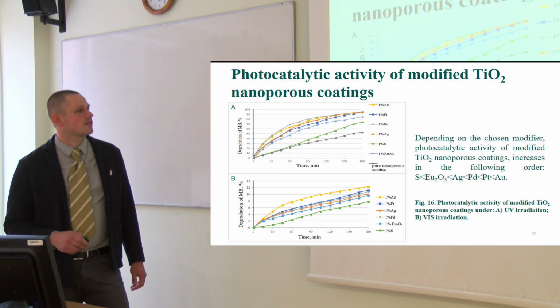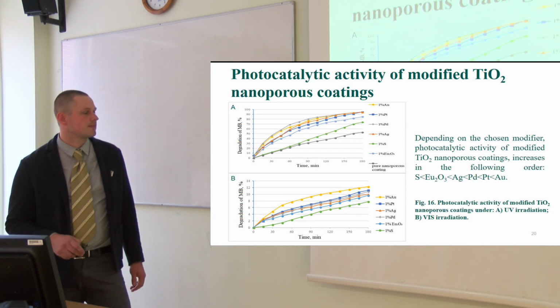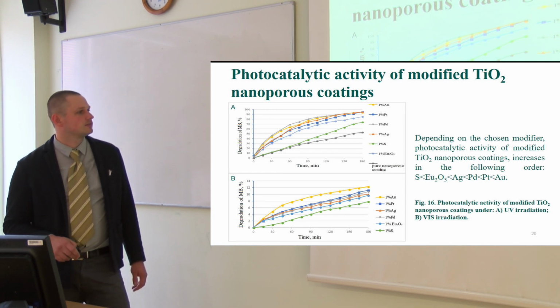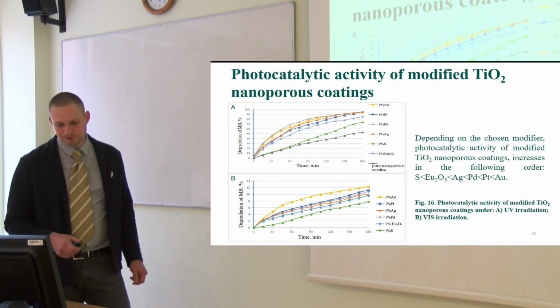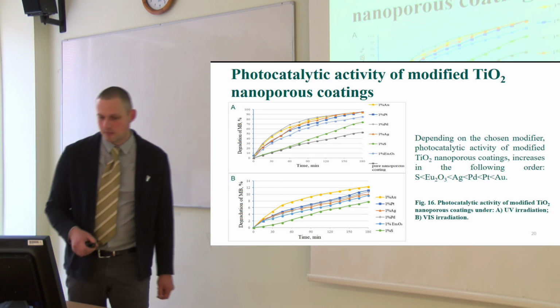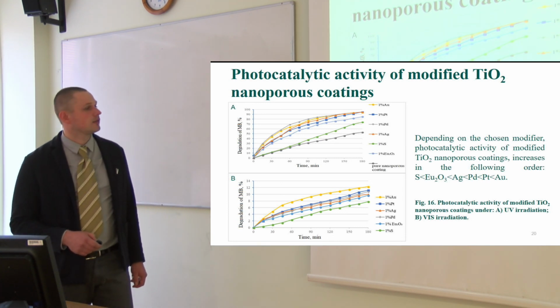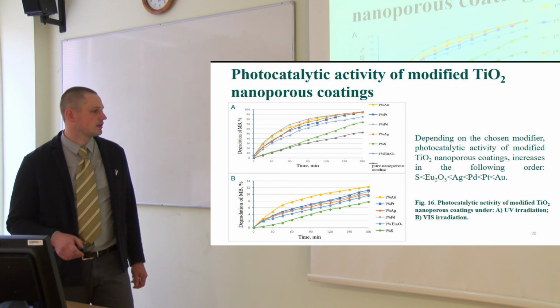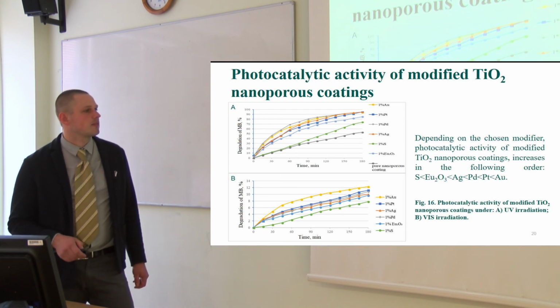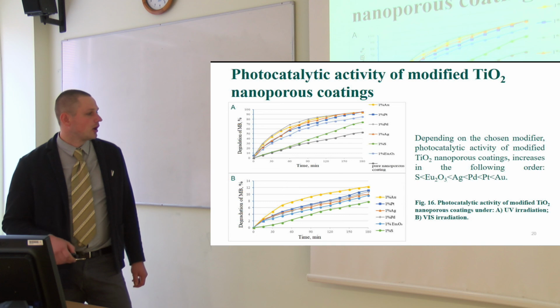And the third graph, here you can see the same photocatalytic activity measurements, but for nanoporous coatings. And also here you can see that this activity is not so high if we compare it with nanofibers, but still we have good activity in visible light for sample modified with gold.